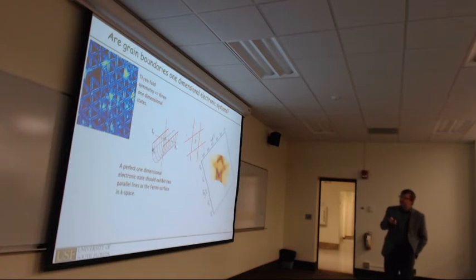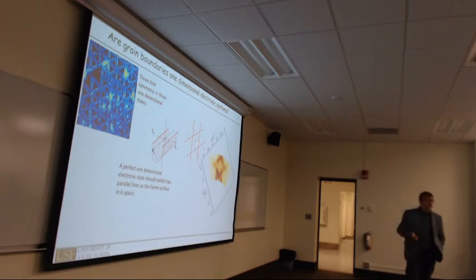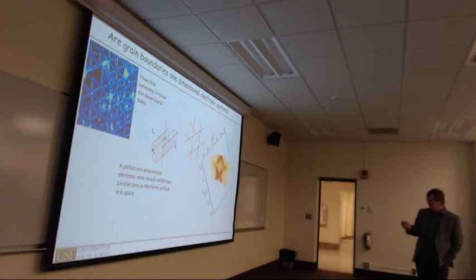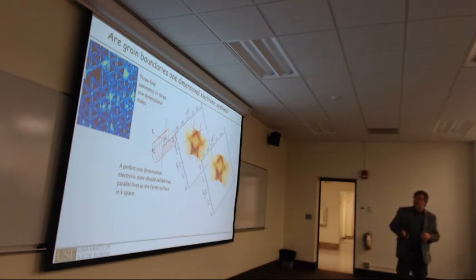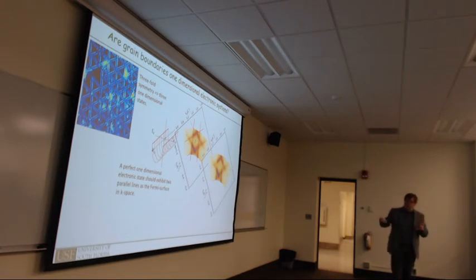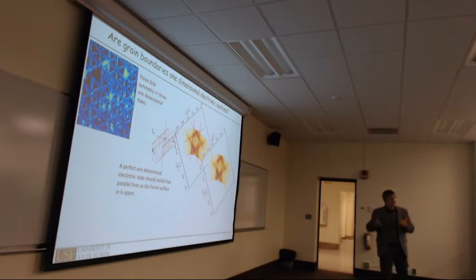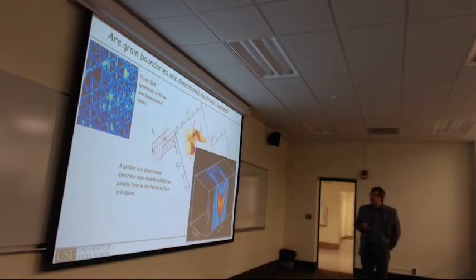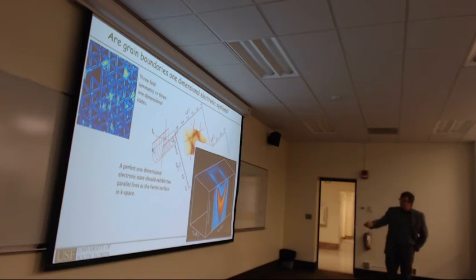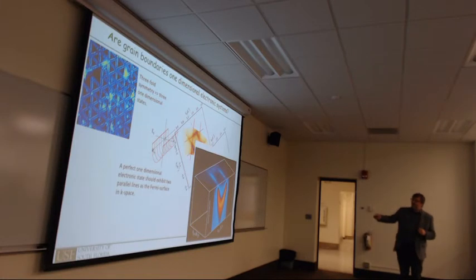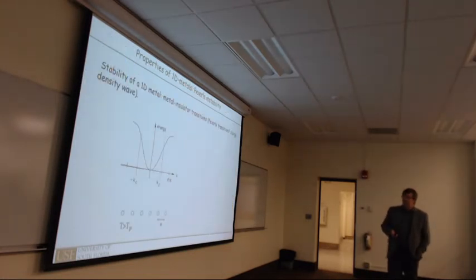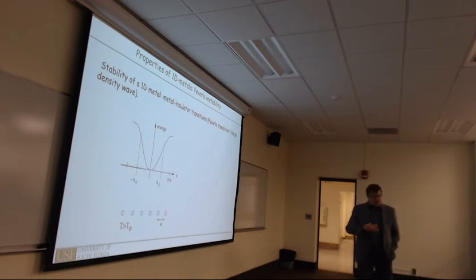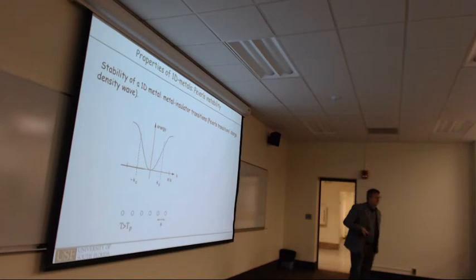So you get three parallel lines. You can measure the Fermi surface with angle resolved photoemission spectroscopy, and indeed you get this cross-hatching of the Fermi surface, whose main point is that you have parallel lines, which indicates it's really a one-dimensional property of these grain boundaries, which you can see here better. So here you have the binding energy, kx direction along the grain boundaries, and then ky, the direction perpendicular to the grain boundaries, and you get these parallel Fermi sheets, indicating it's one-dimensional.